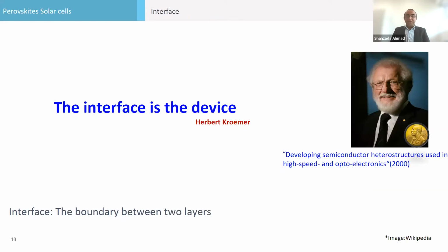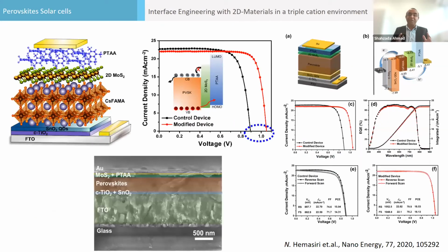Now coming back to the famous saying, the interface is the heart of the device. Here we used a 2D material, not 2D perovskite, but a transition metal chalcogenide material as a very thin interfacial layer. And we put it with polytriarylamine, dopant free, because we want to increase the stability of the solar cells, not only performance. We cannot compare to Grätzel's 25%. By doing this, the energy levels became more aligned and the voltage significantly increased.